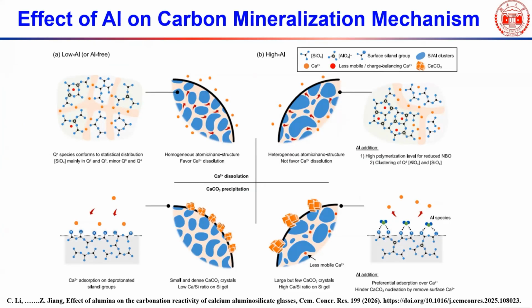Basically, chemically, they explain that without aluminum, the slag will be uniformly dissolved, and so those calcium ions can react with carbon dioxide to form calcium carbonate uniformly on the surface. But if aluminum exists, the surface cannot be uniformly dissolved. It dissolves in big chunks, and so only a small amount of calcium ions dissolve into solution to react with carbon dioxide to form calcium carbonate. But those are very, very rough mechanisms. I think there is still a lot of scientific study needed to really understand the mechanism here.